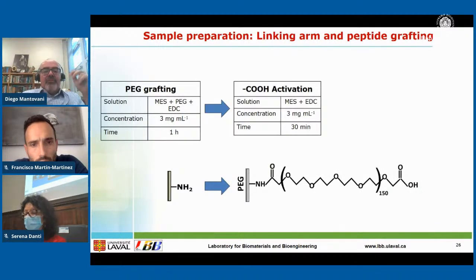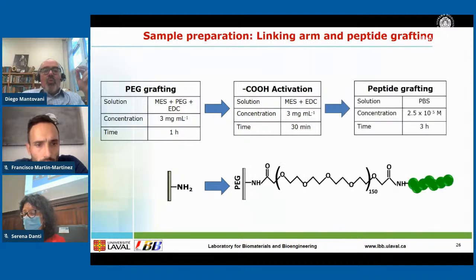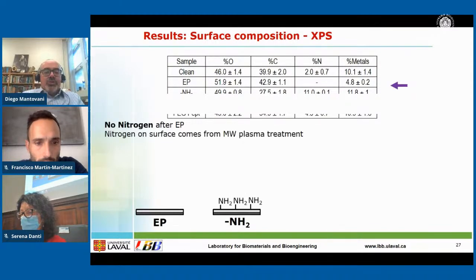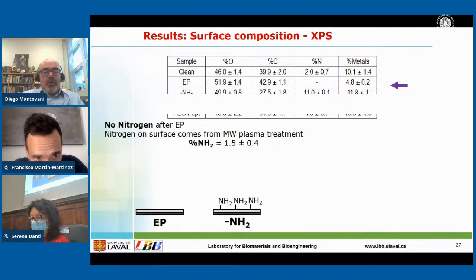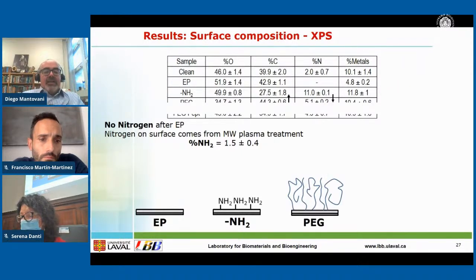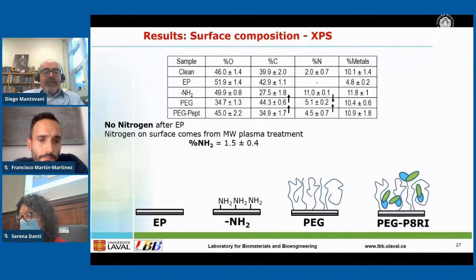And finally, two different linking arms were used for connecting the peptide graft. This is the PEG long chain, and the glutaric acid was second. So in general, no nitrogen after electropolishing. This means that the nitrogen on the surface comes mainly from the plasma treatment. And finally, the PEG is attached, and the PEG peptide is there.